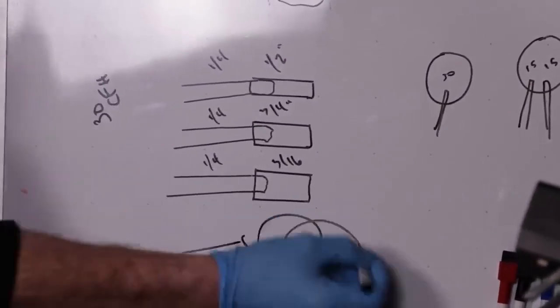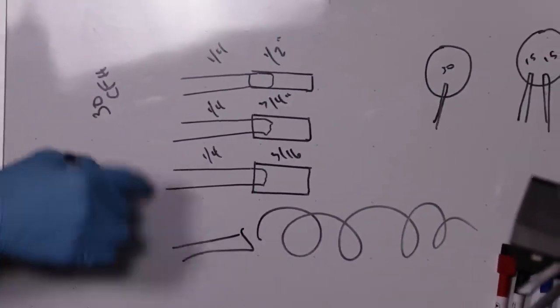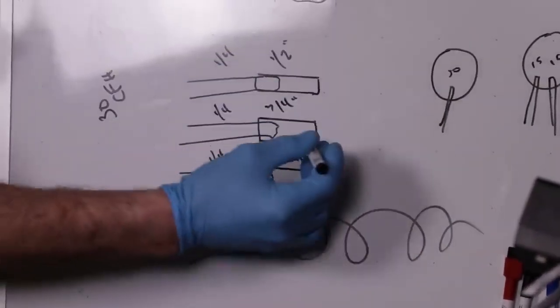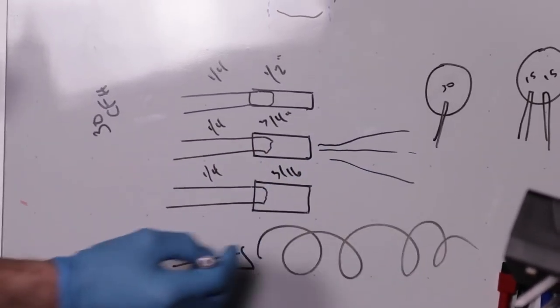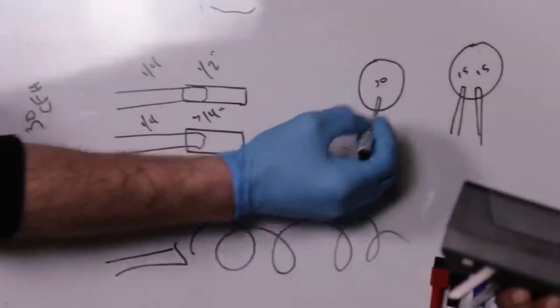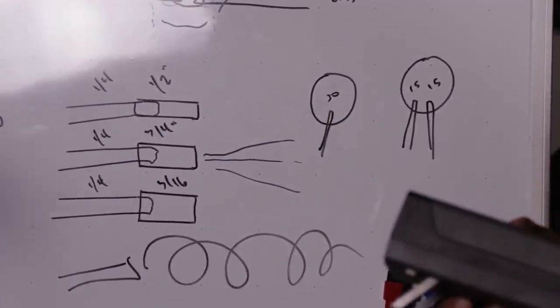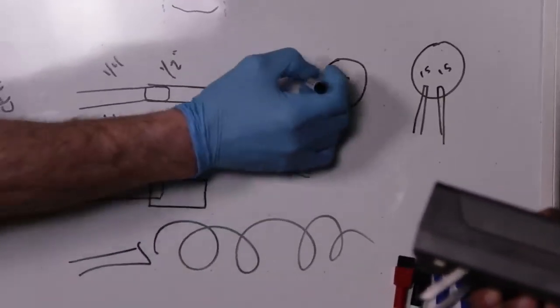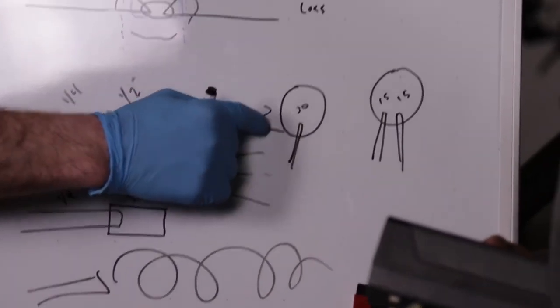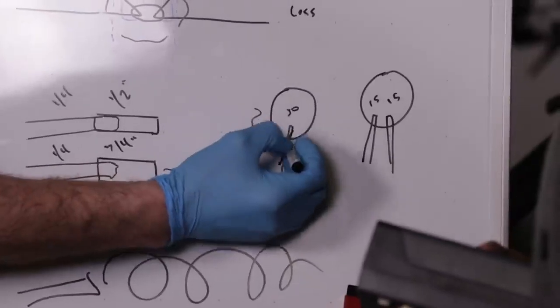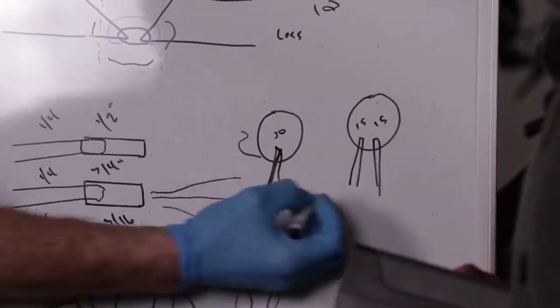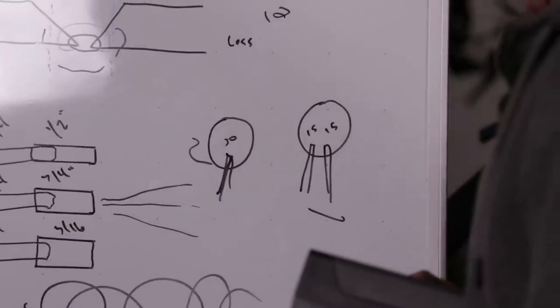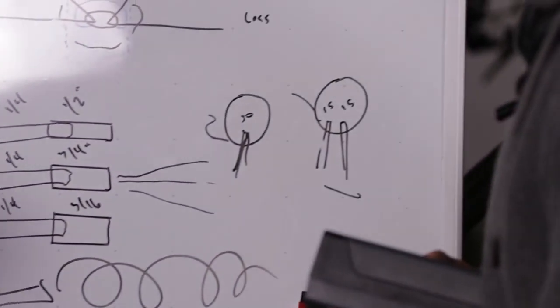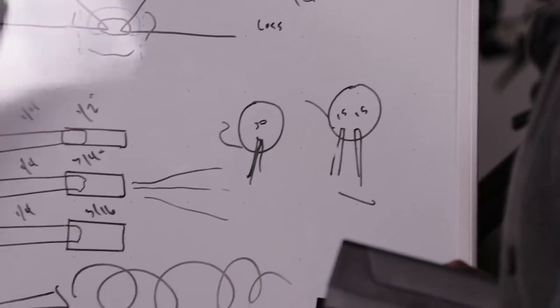So on a 1/4 inch hose it might be quite turbulent with 30 CFH, whereas with a 7/16 or 1/2 inch pigtail the flow may be very gentle. And when you get to a larger diameter pipe, say you've got one hose maxed out at 60 CFH because you need that to protect the inert atmosphere, and depending on how much tape you remove, you need to replenish that amount of inert atmosphere within the pipe. Rather than one hose at 30 CFH, you could use two hoses at 15 CFH each, and it softens the flow coming out of the hoses. You can also include a pigtail of a different ID hose, maybe 1 foot long, and that makes the flow from a larger ID hose a lot more gentle. So these are different variables that need to be considered.